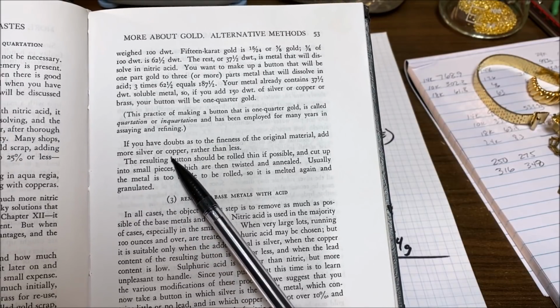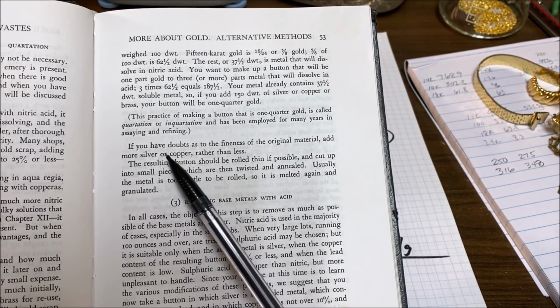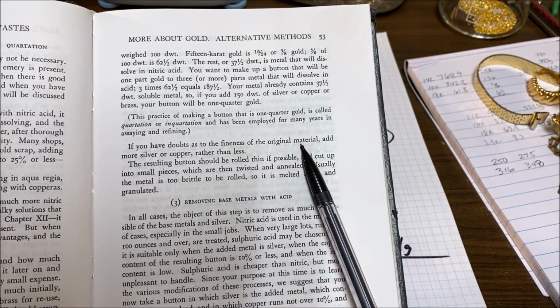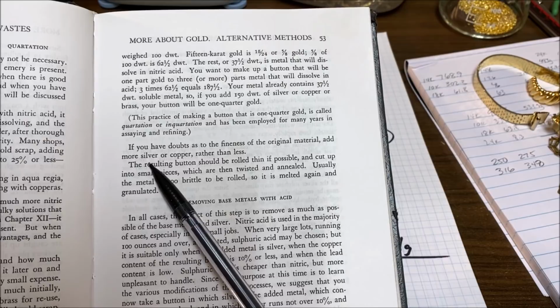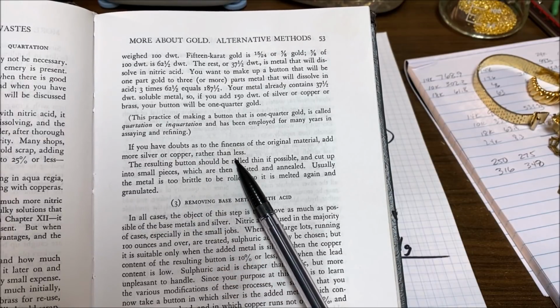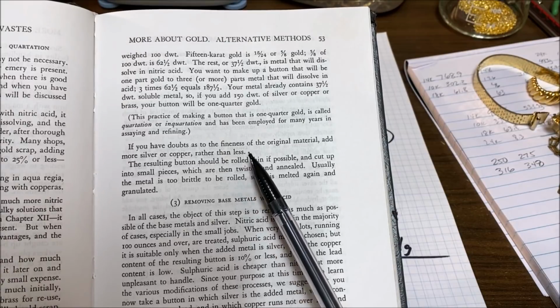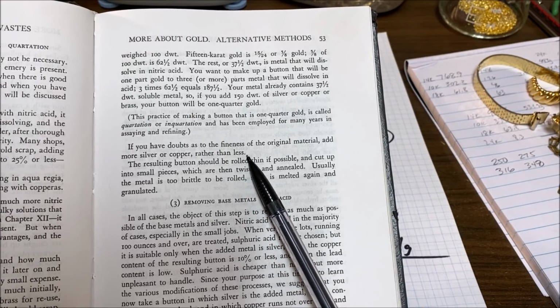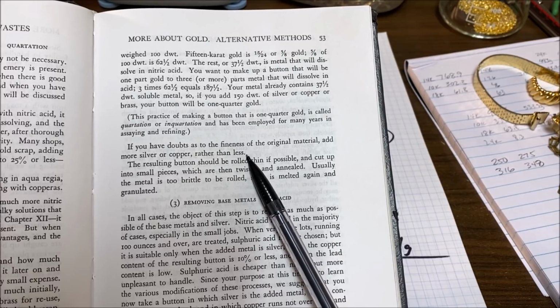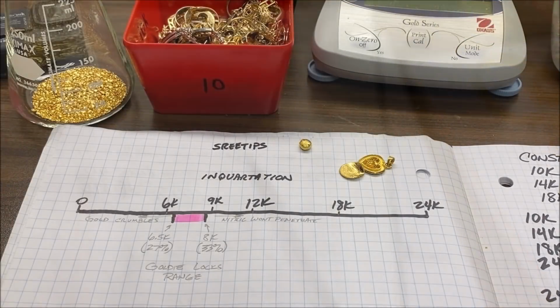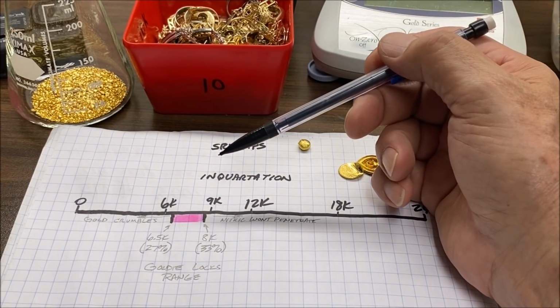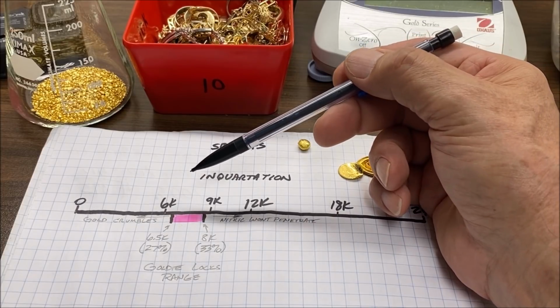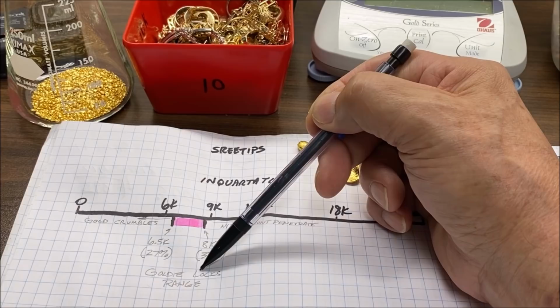This is the only thing that I disagree on in this book. It says if you have doubts as to the fineness of the original material, add more silver or copper rather than less. And in my experience, if you add too much silver, the inquarted gold will fall apart, crumble into a powder, and cause problems when we try to separate the silver solution that sits on top of the powdered gold.